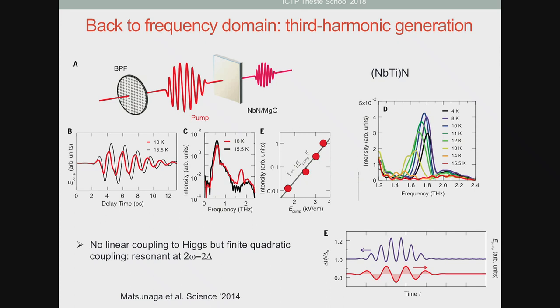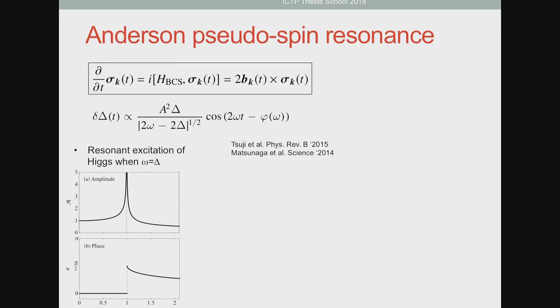So here, actually, it's a sizable signal. And it's only activated in the superconducting state. So, actually, the theory of this effect was worked out by Tsuji and Aoki. And what they show is that if you use the Anderson pseudo-spin formalism, you can actually compute the nonlinear current. And they show that the third order nonlinear current is actually directly linked to the oscillation of the amplitude of the gap. And importantly, this oscillation of the gap is resonant when the frequency of the incoming light omega is exactly equal to delta. So you shine light at delta, and you collect light at 3 delta.